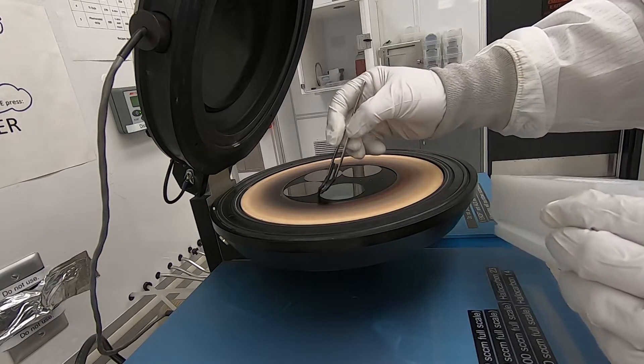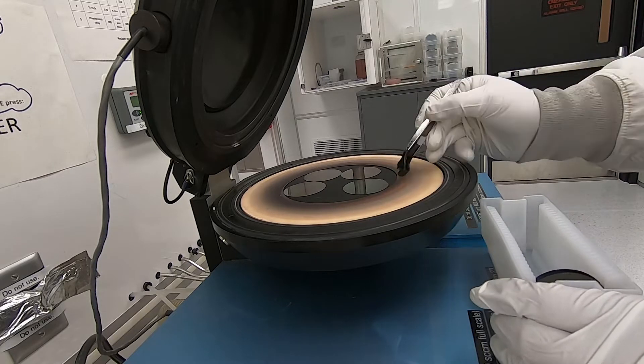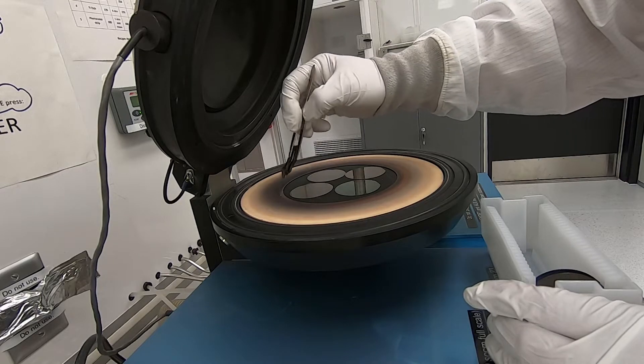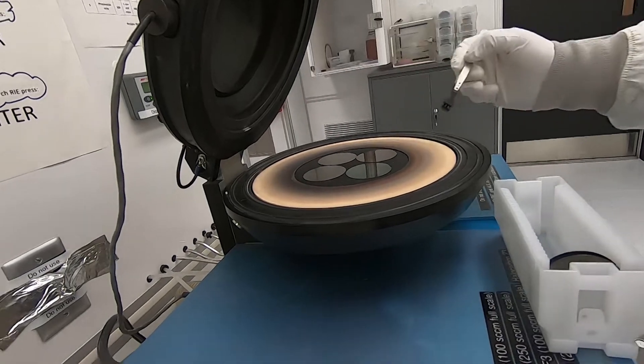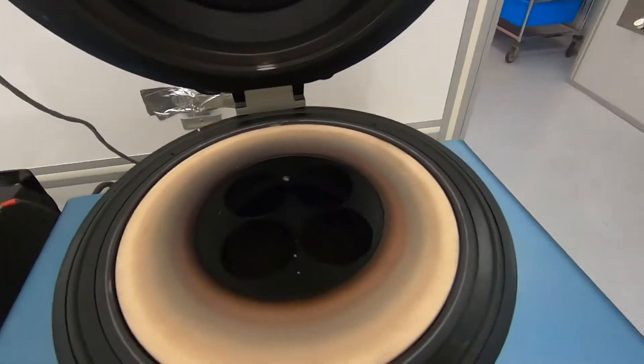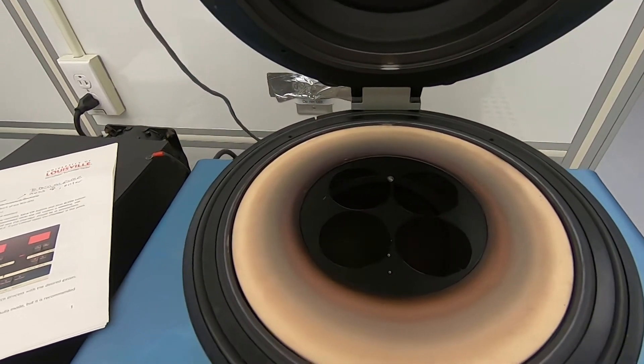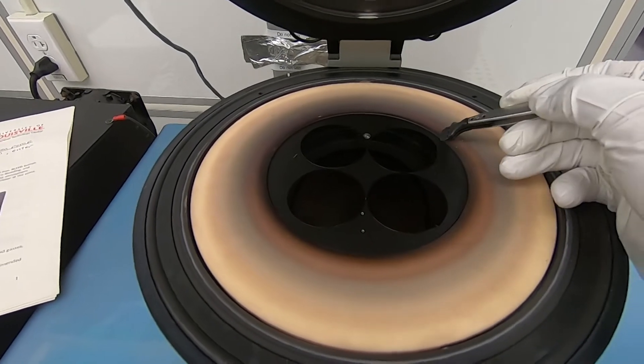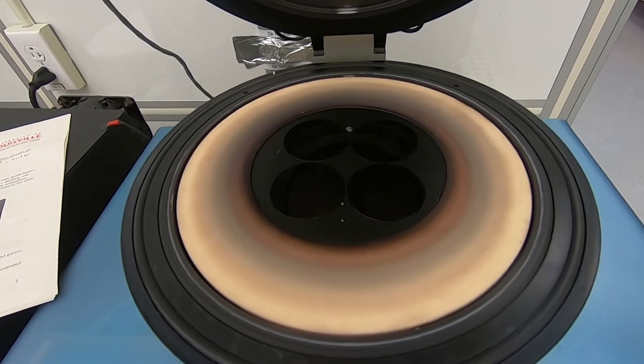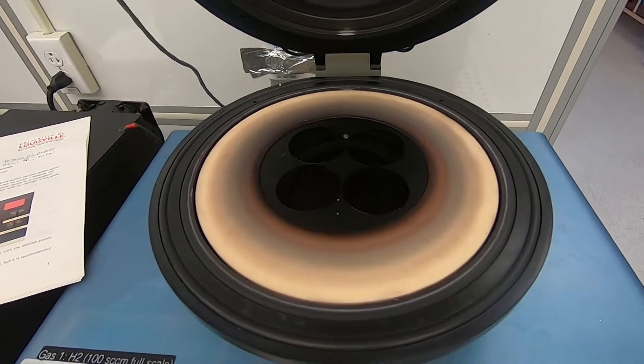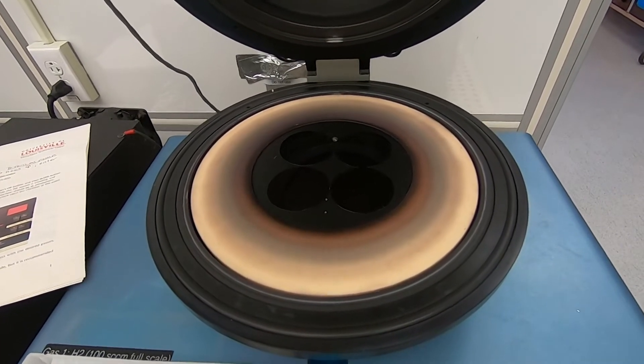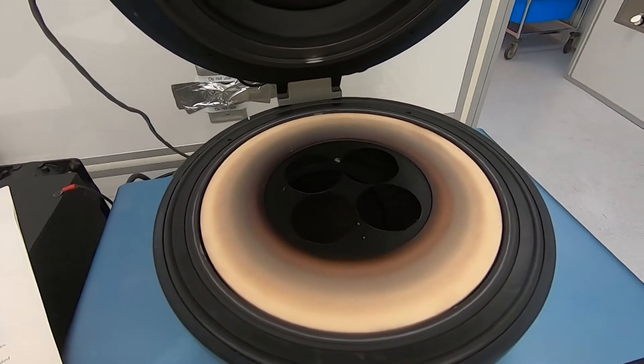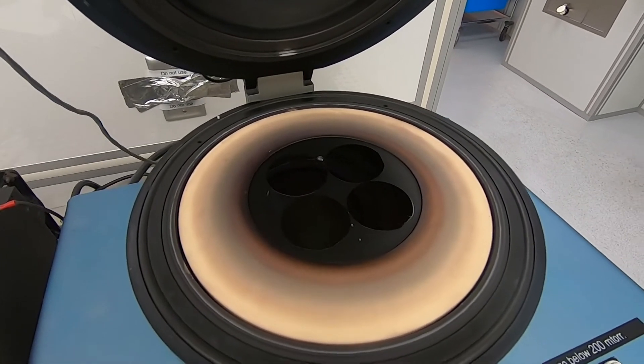Now shoot, they're not going to fit. So you can only put four in. One little point about reactive ion etching: if you are at the edge of the electrode, the chemistry gets a little wonky and you end up with more sputtering than reactive ion etching. So you never want your wafer to overlap the edge of the electrode, you kind of want to stay away from the edge of it. This is going to go on for five minutes to strip all the resist off, and then the next step will be an RCA clean.